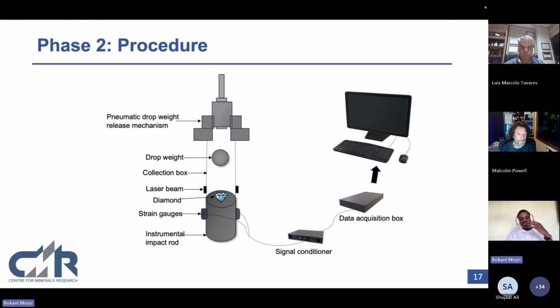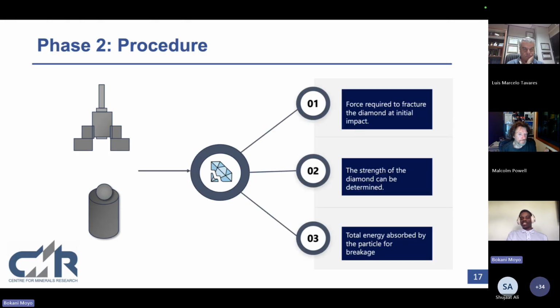So this on the slide is essentially a schematic of a short impact load cell, right? It's a very simple construction. And then from there, all it does is you drop weight and then you break your diamond, and then you can get essentially 3 parameters. So we can get the force required to initially fracture the diamond, the strength of the diamond, as well as the total energy absorbed by the particle for breakage.